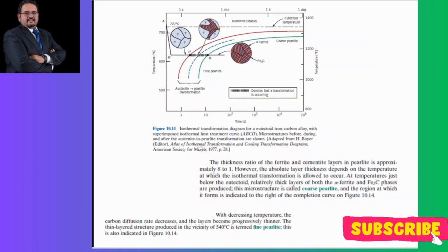This is another representation of the TTT diagram, which is the time, temperature, and transformation curve or diagram. It was gamma here. So students, some of you are confused in this region, what is this region, right? This whole region that I have shaded is basically the unstable gamma. That is still gamma, but gamma has to change. So that is unstable. It cannot stay like that. So the moment it crosses this boundary, this is where conversion happens. Gamma converts into the lamellar structure of pearlite.